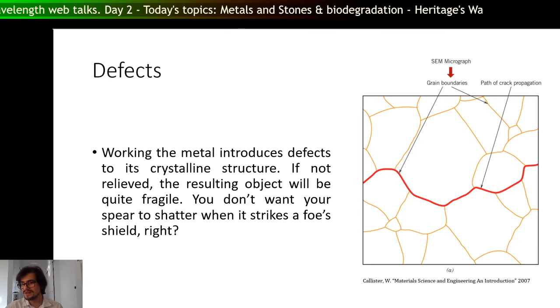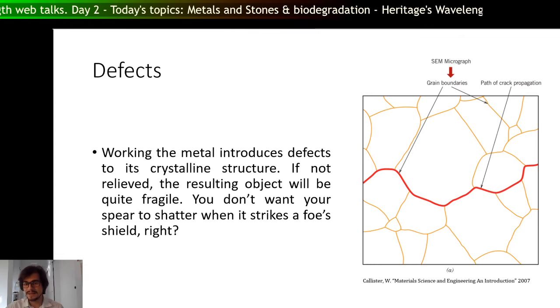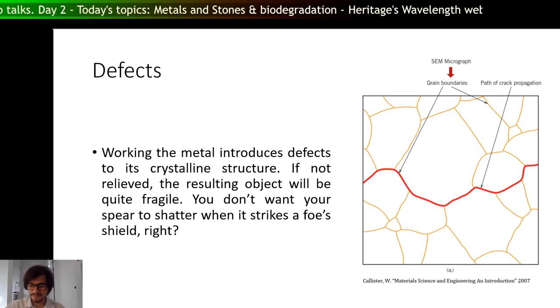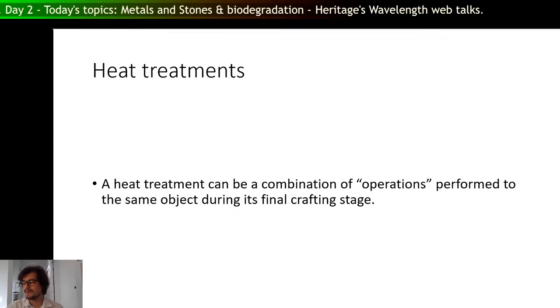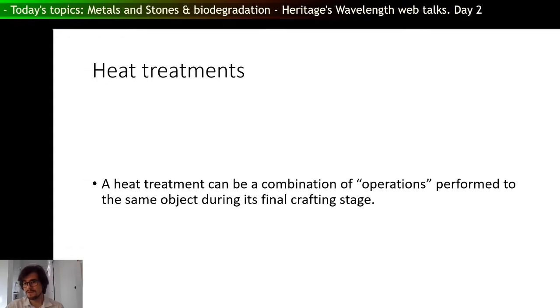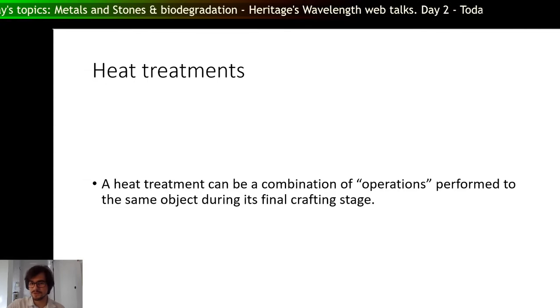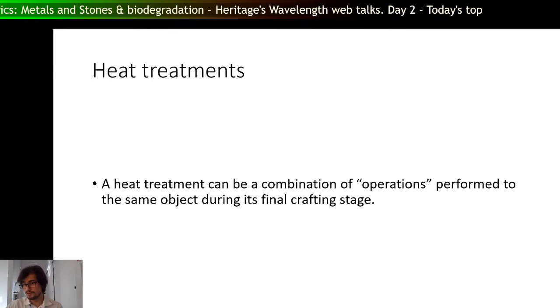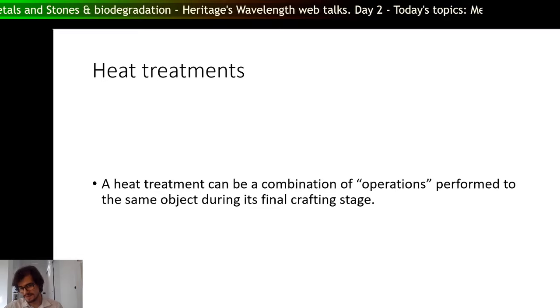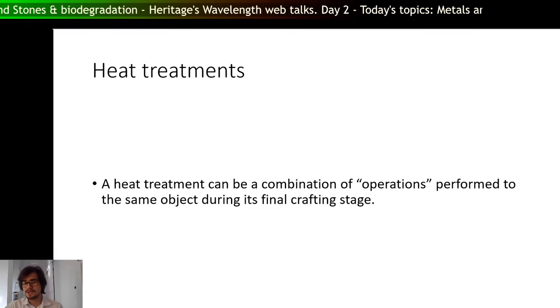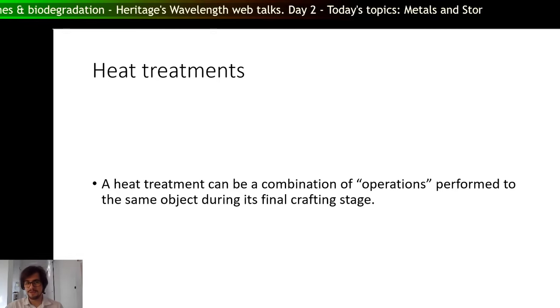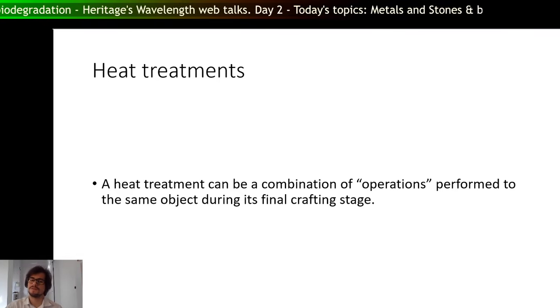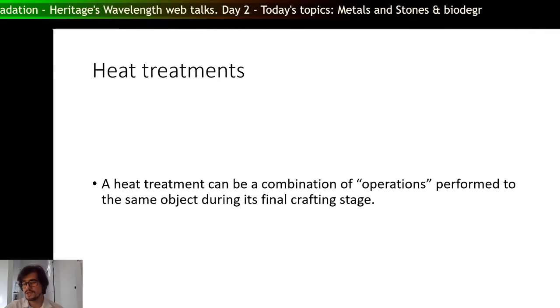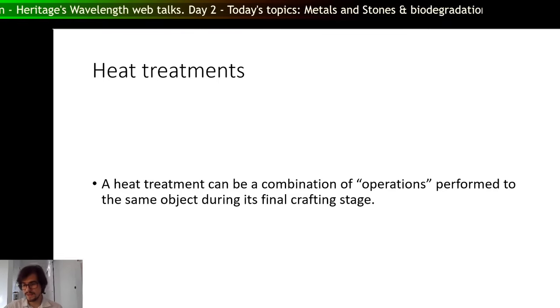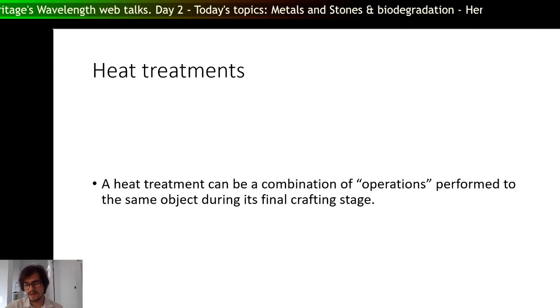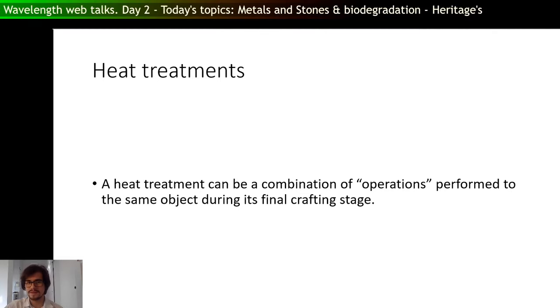So you want a good quality metal. You want a metal that is ductile, stiff, and very strong. And that's where the capacity, the technological level, the skill of the weaponsmith comes in. That's why you have fancier swords, like king swords with adornments and a very good metal, and you have those cheap ones that can shatter at any given minute. A good quality metal is achieved by heat treatments. It is a series of operations performed on the same object during its final crafting stage. So you're applying heat to it, you're cooling it, giving and taking heat, and then hammering once again until you reach the perfect state you want.